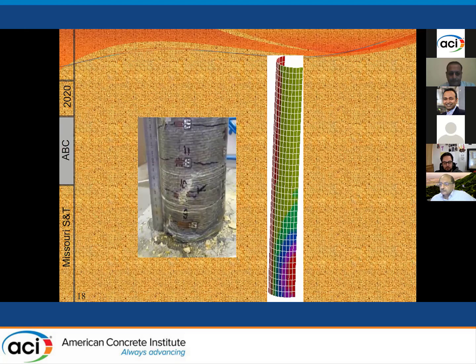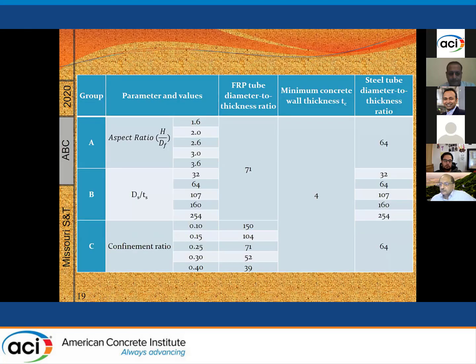So in addition to looking at the hysteretic performance, we also look at the mode of failure. Was our model correct in predicting the mode of failure? This is one of the columns where FRP rupture occurred, and it occurred at the very bottom. Our model showed that wherever we have these red shells, that indicates a stress concentration, which indicates rupture of the FRP. This was after we did the calibration against more than 10 columns.